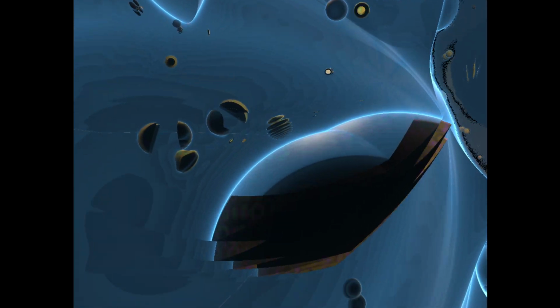Hund's coupling. That favors electrons having aligned spins in different orbitals on the same atom, doesn't it? Exactly. It wants to maximize the total spin on the iron atom. And this Hund's coupling has profound effects. It tends to suppress electrons hopping between orbitals if it messes up the spin alignment, but it doesn't hinder spin fluctuations as much. Okay, so what does that lead to? It leads to a state that's neither a simple metal with freely moving electrons, nor a Mott insulator with completely stuck electrons. It's something in between, this Hund's metal.